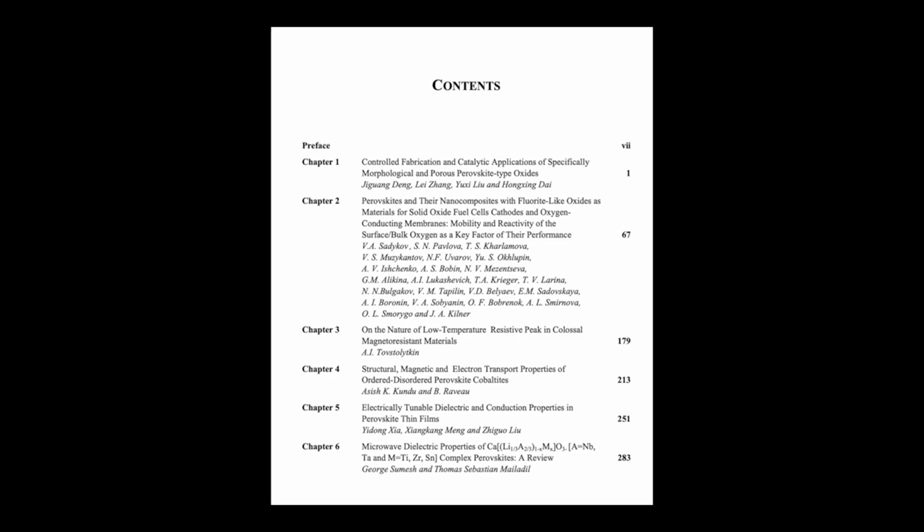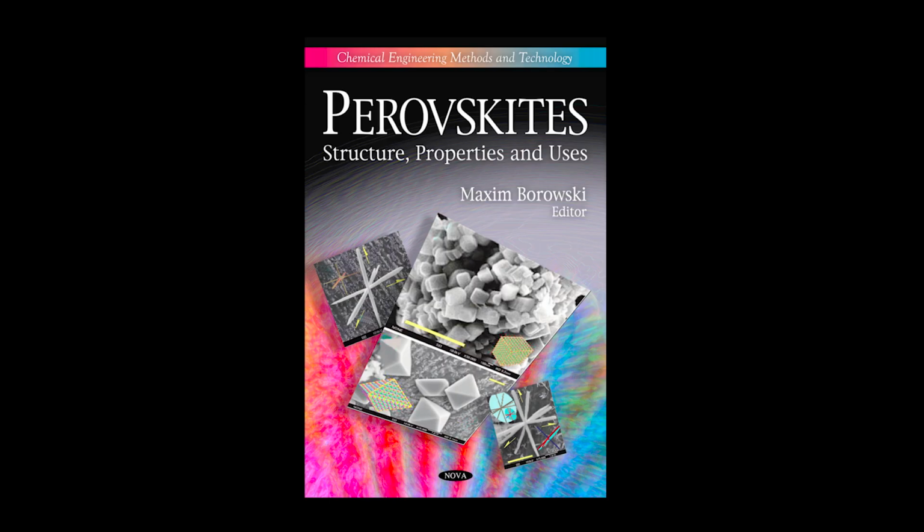We define the ideal perovskite structure as cubic, belonging to the space group Pm3̄m. In this ideal setup, the B site cation is perfectly nestled within 6 surrounding X anions, forming this pristine corner-shared BX₆ octahedron network. Beautifully simple. But in real-world scenarios, due to changes in composition, temperature, or pressure, the structure almost instantly starts to distort. It just doesn't stay perfect.